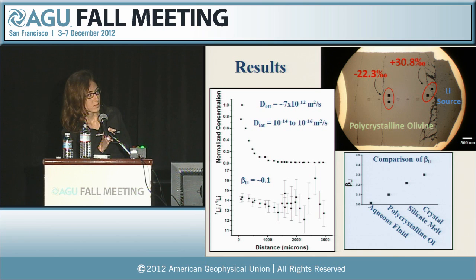Up here in the top right, we have our first ion probe analyses data. So this is the scale bar here. This is 300 microns. This time the lithium source is on the right and the polycrystalline olivine is on the left. And so we had 2 spots analyzed really close to the source and 2 spots analyzed far, about 1,500 microns away from the source. The 2 spots close to the source yielded a delta 7 lithium value of about plus 30 per mil, whereas the one further away from the source yielded a value of about negative 22 per mil. So very large fractionation over a very short distance.